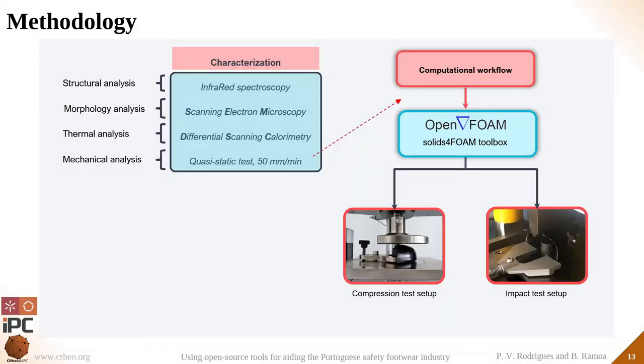For the methodology, firstly, the identification of the material was carried out through infrared spectroscopy and differential scanning calorimetry. And we used scanning electron microscopy to detect possible reinforcements in the polymeric matrix. The mechanical characterization was performed at 50 millimeters per minute to define the stress-strain behavior of the material and to better approximate the material behavior after heating. Afterwards, the computational toolbox for fluid-solid interaction built within the OpenFOAM framework, which was solids4foam, was used for modeling the impact and the compression tests.